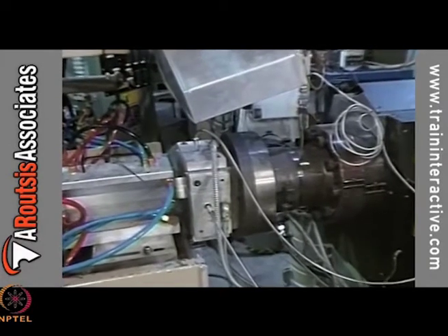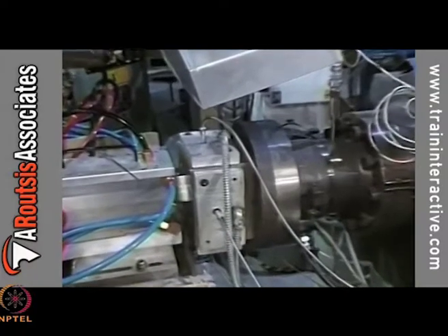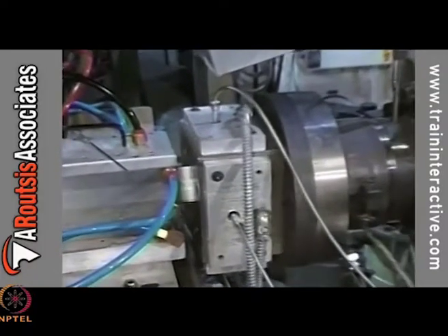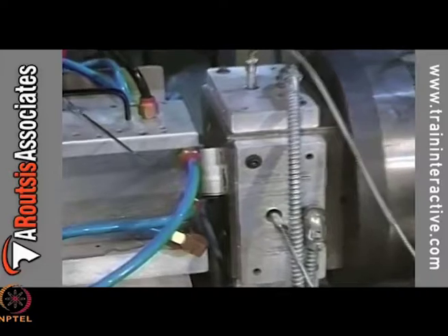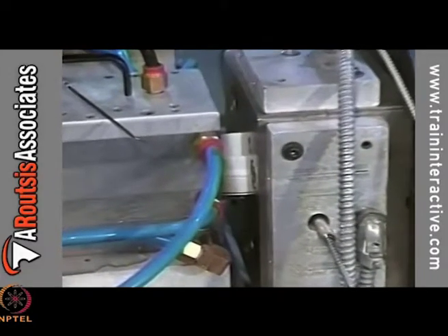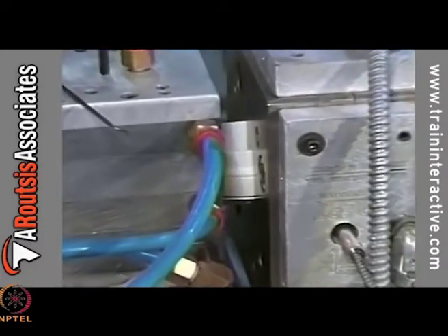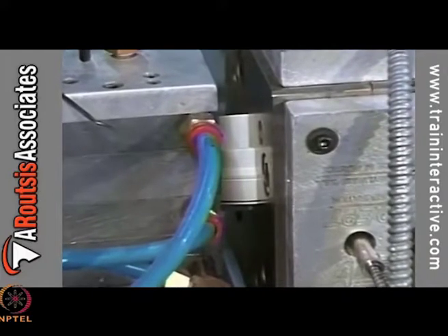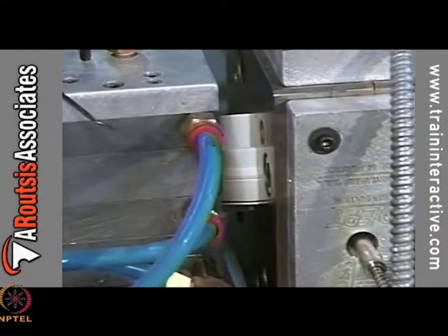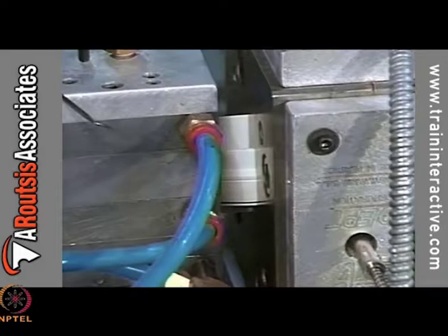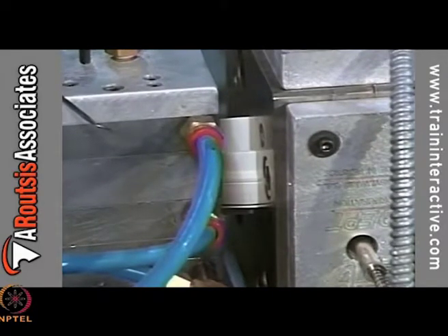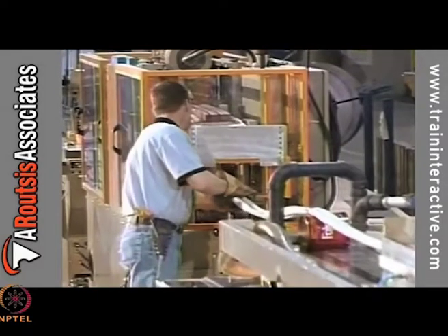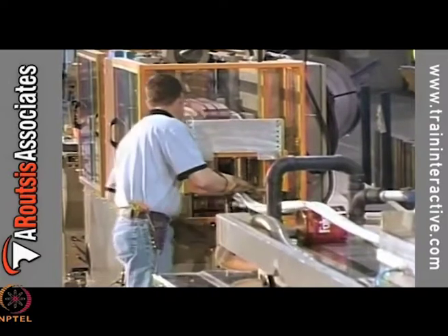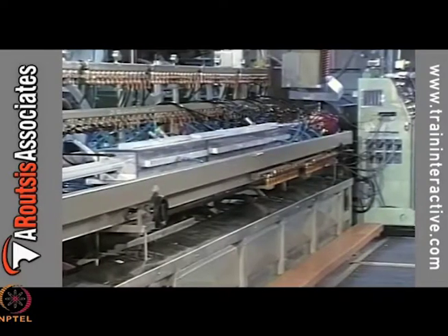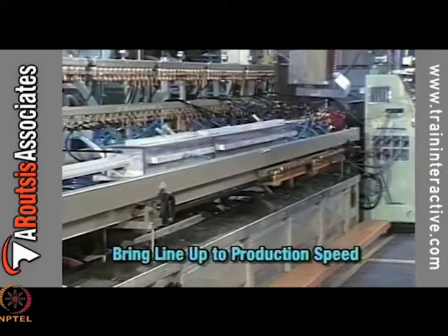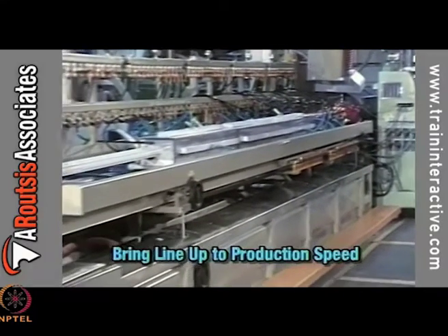Once plastic is flowing from the die, gradually increase the screw speed. You may be required to let it run at some lower speed until the material is flowing smoothly from the die. If smoke, black material, streaks, or snapping or popping sounds continue, there may be a problem. If they clear up in the normal amount of time, thread up the line and start the downstream equipment if it is not already running. As soon as possible, bring the line up to production speed and closely monitor both the process and the product.